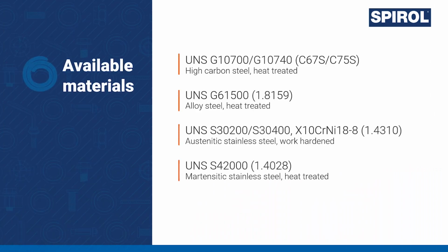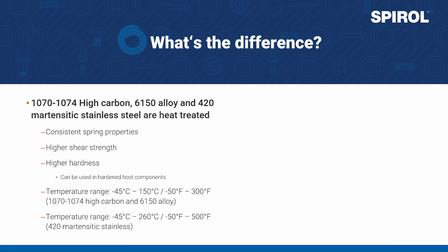Another factor determining service life of the application is pin material. Coil pins are available in high carbon steel, chrome vanadium alloy steel, and 2 kinds of stainless, austenitic nickel stainless steel and martensitic chrome stainless steel. Some of these materials are heat treated, which improves overall performance and consistency of spring characteristics. Heat treating provides higher shear strength and hardness, resulting in pins that are suitable for use in hardened host components.